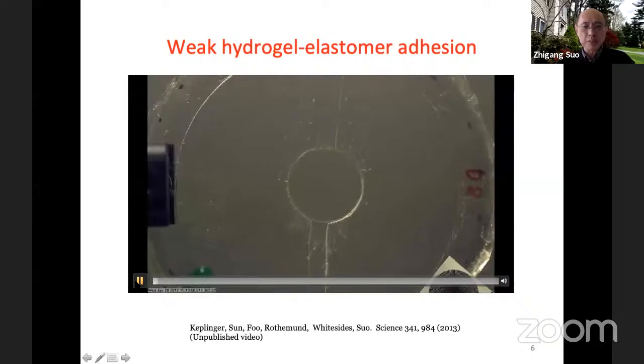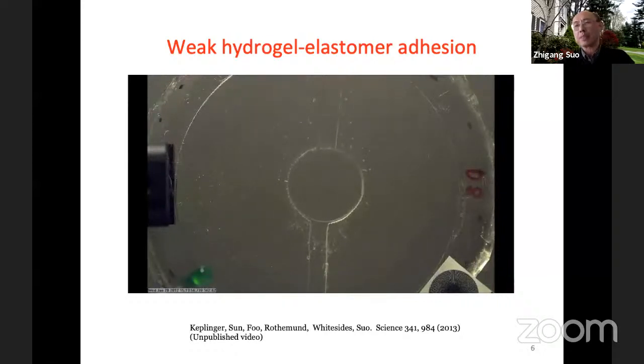So you can see from this video, you can see the vibration caused by cyclic voltage. You can see debonding - the hydrogel comes off the elastomer. The adhesion is just a van der Waals interaction. We did not publish this. We said, okay, if we try this a little bit, the adhesion becomes better. It's not great, but at least it doesn't do this during the demonstration. That was good enough for the paper.